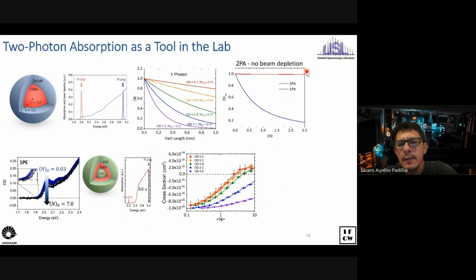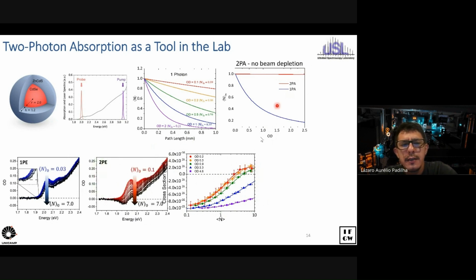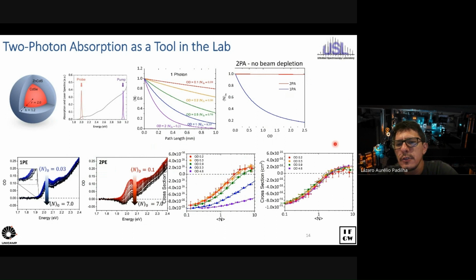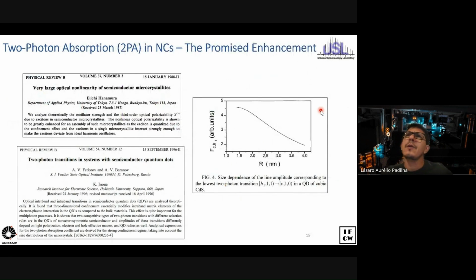So what happened here is that if you try to measure gain, you get very nice gain curves, even for a very high concentration sample, because the optical density for this is 0. And just to compare, here are the same curves done by 1-photon and by 2-photon. You see the 2-photon pump curves all fall in the same trend, because basically the sample doesn't care about the concentration when you're exciting by 2-photon absorption. But the question is, how strong is 2-photon absorption in nanomaterials?